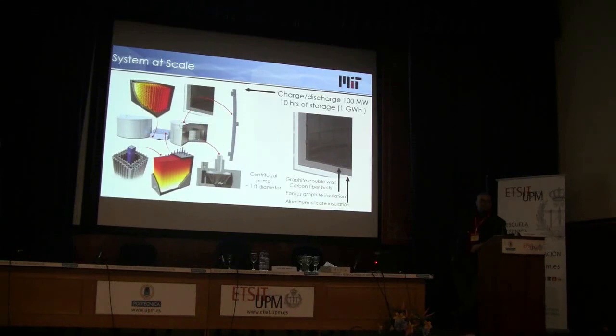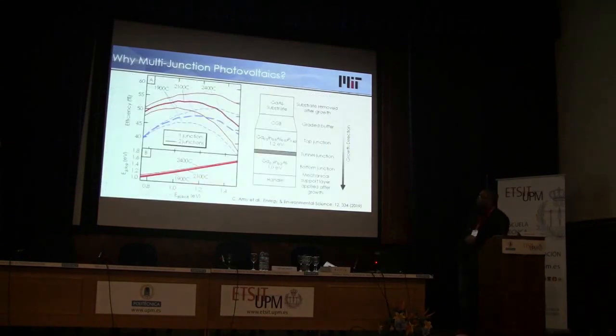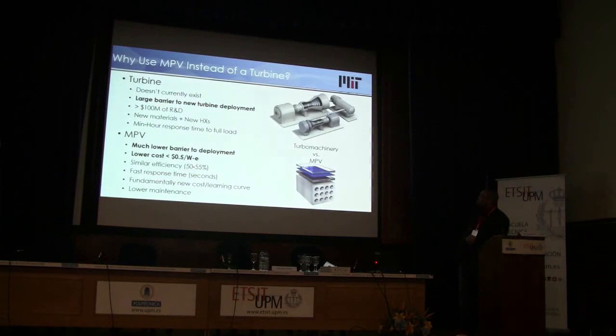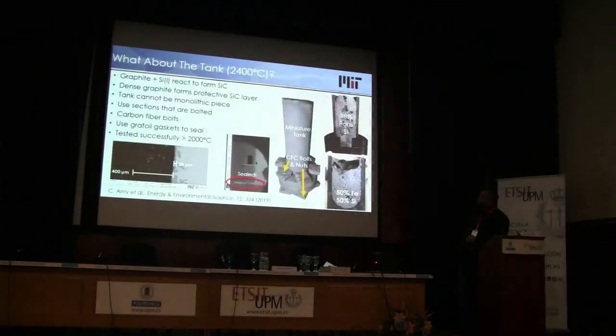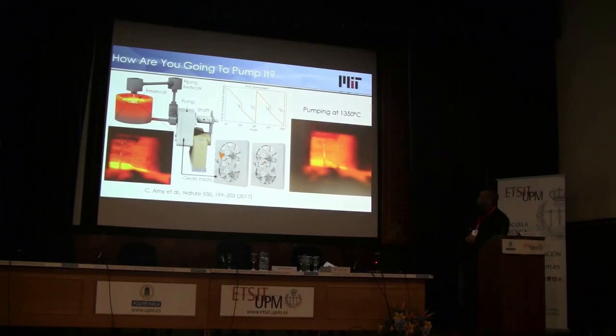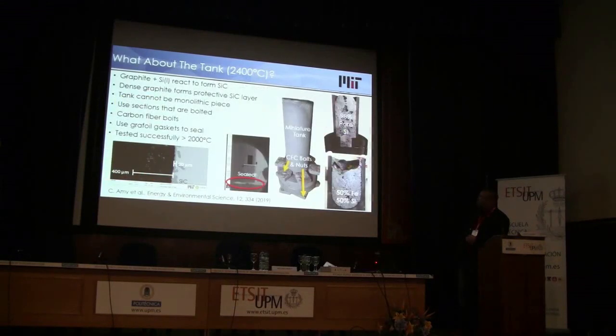The microstructure of silicon inside the refractory container or tubes. There are many pores, and can you explain the reason for this porosity inside solidified silicon? Yes, in a tank, probably in tubes. And another question is, do you observe silicon carbide particles inside due to the movement of molten silicon for a long time at such an extremely high temperature?